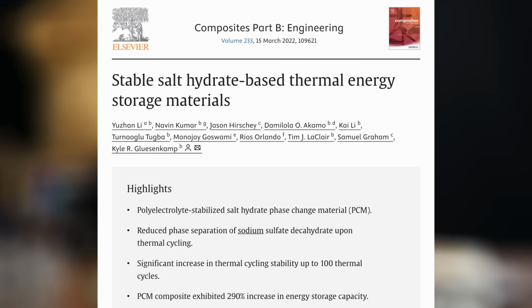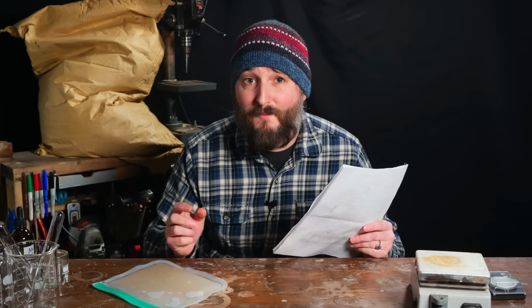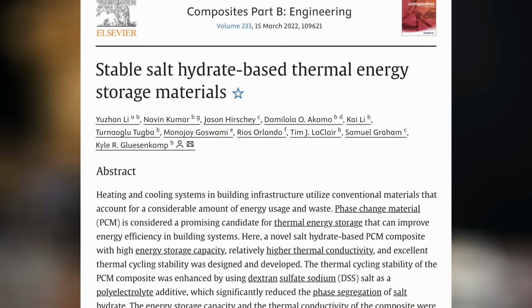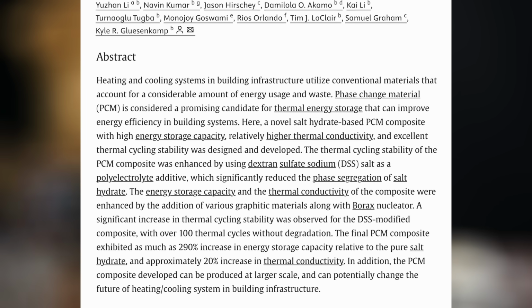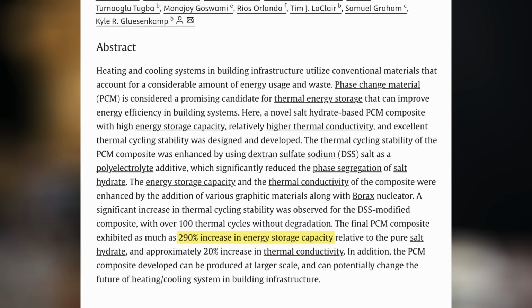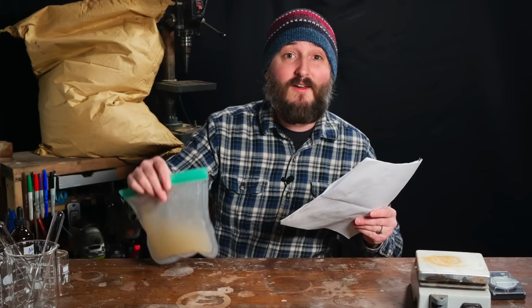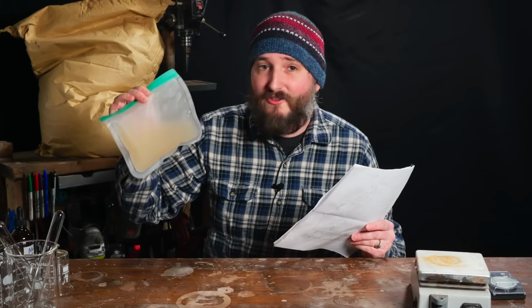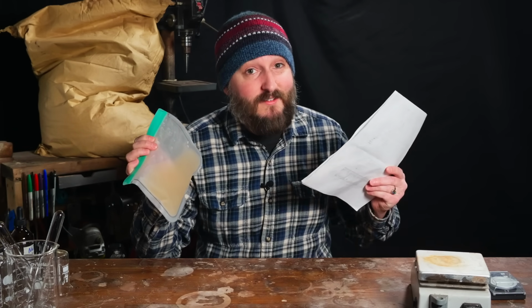Now, in the last few years, one scientific paper seems to have stumbled on a massive breakthrough. This paper, which is titled Stable Salt Hydrate-Based Thermal Energy Storage Materials, not only reports that they've made a sodium sulfate PCM, which shows no loss in capacity over at least 150 freeze-thaw cycles, but the starting capacity itself has been increased by 290%. The storage capacity of these cold packs we made previously is already impressive. This is unbelievable.